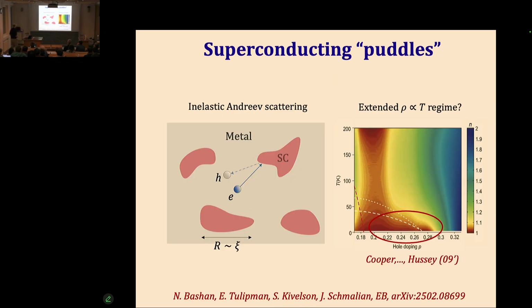So our idea is to think of the following. Suppose we suppressed superconductivity either by raising temperature or at low temperature by raising field. We destroyed the global phase coherence of the superconductor, but not the local pairing in these superconducting islands. And our conduction is now mostly carried by the normal part of the sample, by basically a normal metal. But electrons from this normal metal will scatter off these superconducting islands. In particular, they would Andreev scatter. And it's this Andreev scattering, in particular inelastic Andreev scattering of the electrons, that's the source of the linear T resistivity.